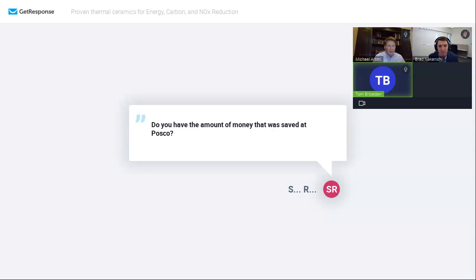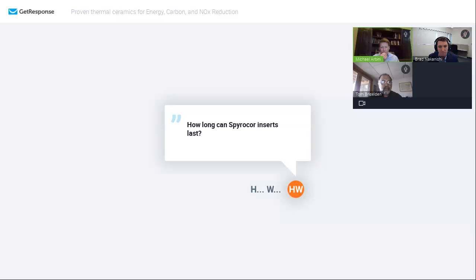A typical question, Tom, that comes up in some of the other webinars has been lifetime of not only Spyrocor, but ceramics in general. Can you expand on that? So the Spyrocor, when applied in a radiant tube, it will outlive the life of the radiant tube. And then our customers really have two choices. As they see the radiant tube failing, which usually occurs between 3 to 5 years, they remove the Spyrocor, put in new tubes, and replace the Spyrocor. We've had customers successfully do that for anywhere between 2 and 3 tube changes. If the tube does fail, a lot of times it'll capture the Spyrocor, and sometimes you can't recover it, but sometimes you can. But we've had Spyrocor in operation in this environment for over 10 years now.